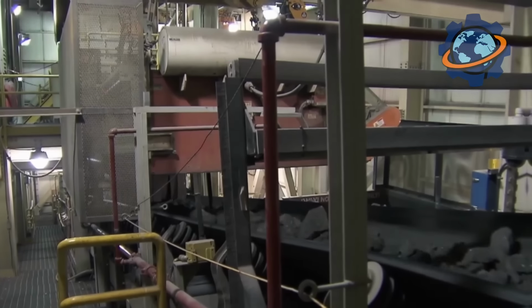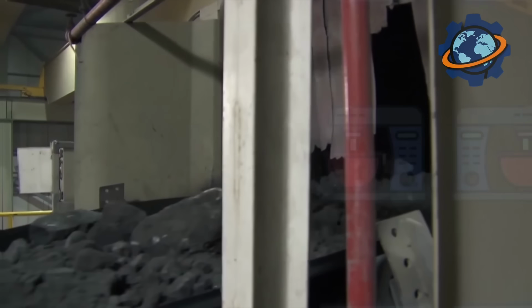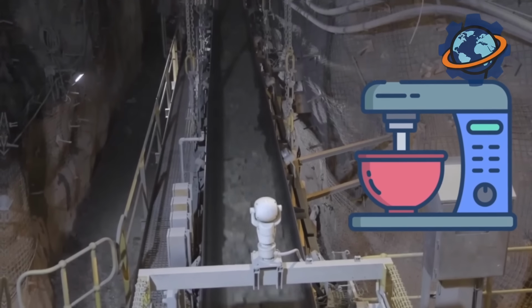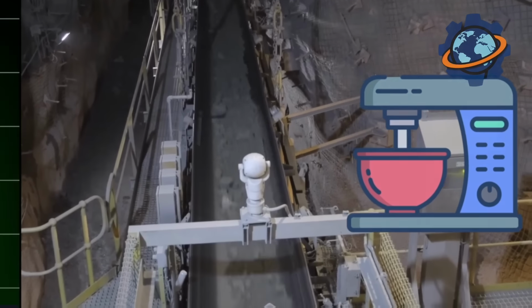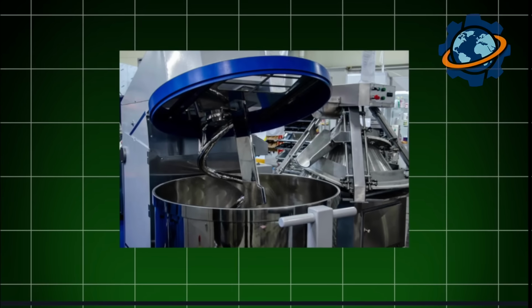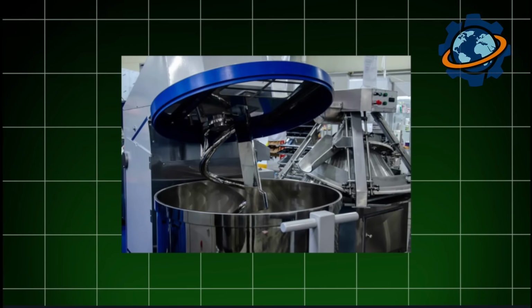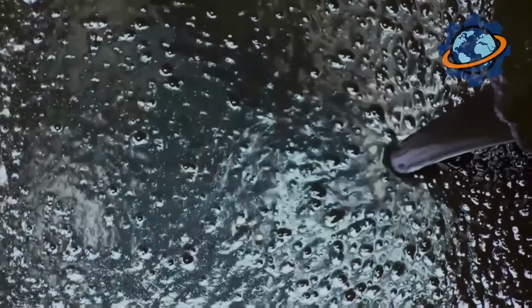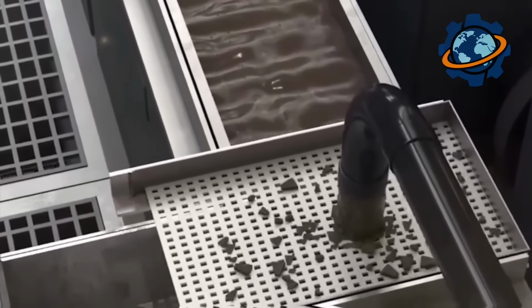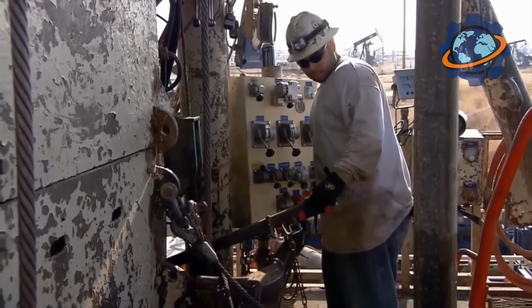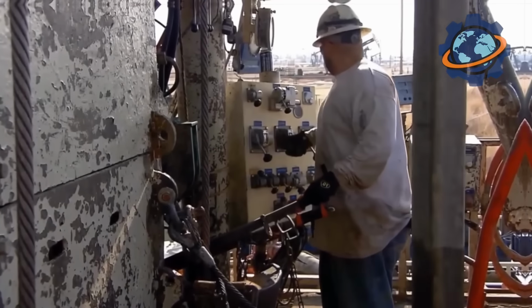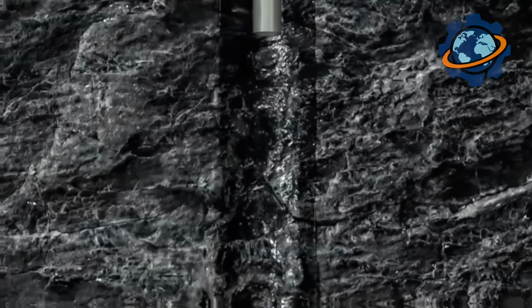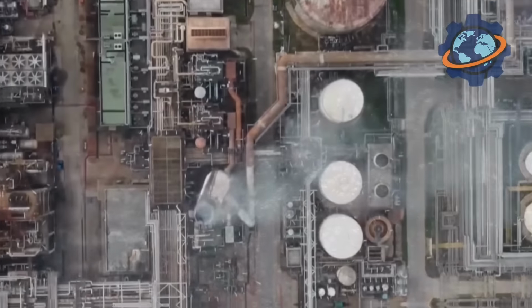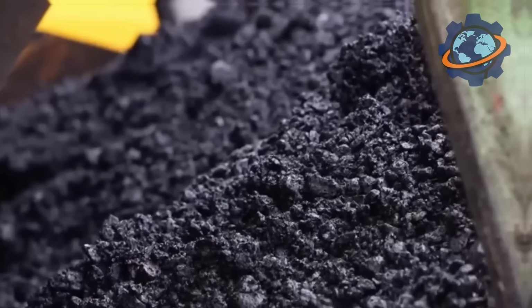This entire mass, stone and bitumen, is dropped into a mixing chamber called a pug mill. It's like a giant kitchen mixer, but instead of whisks, it has 2 powerful shafts with metal paddles. These paddles churn the hot mass with enormous force, and in less than a minute, every single stone, every grain of sand, is coated in a thin, shiny film of black bitumen. Out of the chamber comes the finished asphalt, a uniform, steaming black mass with a characteristic oily smell.